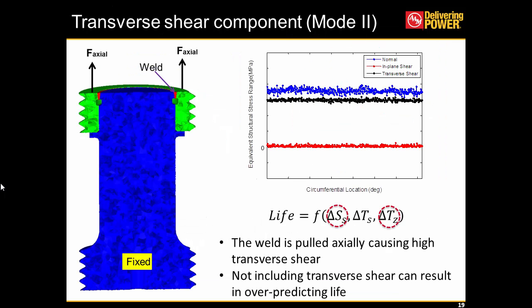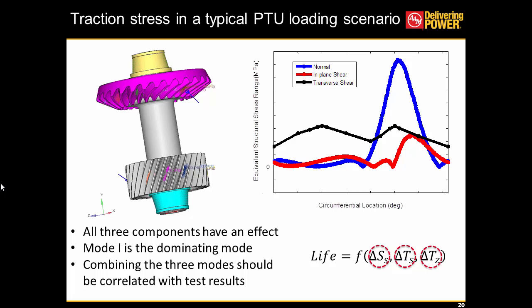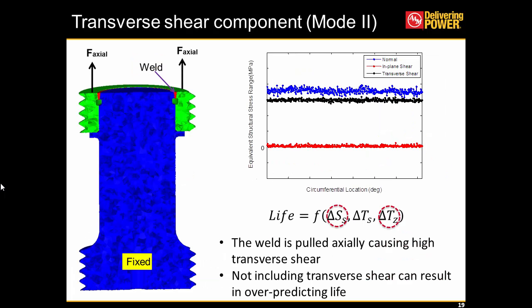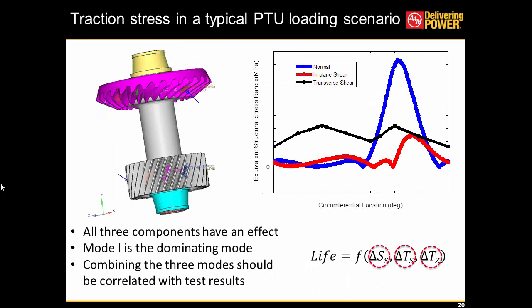And our third case is a transverse, mode 2 load dominant scenario, where we have a component which is fixed at the bottom and welded to the gear, and it's pulled axially. We observe that there is a very high transverse shear effect. The preliminary results had shown that if you don't consider the effect of transverse shear, then this will be over-predicting the life.